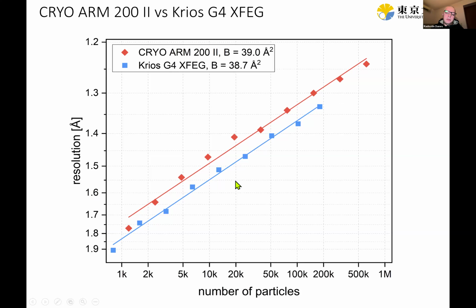And the second data set we evaluated was from our Krios version 4, Krios G4, which has a Schottky FEG. So it's not a cold FEG. With this one, we also got a B factor of 38.7, so virtually identical to the one of the Cryo-200 version 2. Now you see that the curves are a bit offset vertically, and this would mean that the overall signal-to-noise ratio in the data for all the spatial frequencies is a bit higher for the Cryo-200. Basically, it needs a bit less particles to reach a given resolution than the Krios dataset.